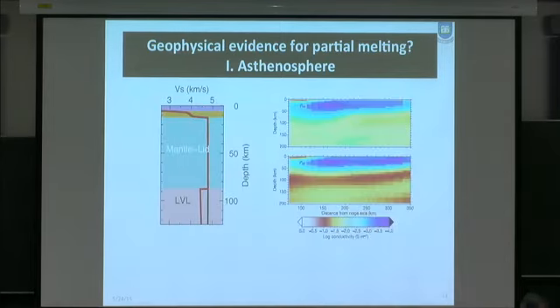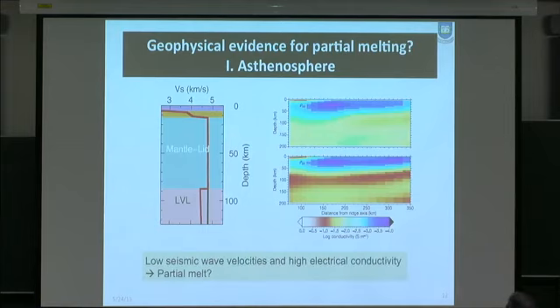Geophysical evidence for partial melting. There are a few observations. One is the seismic velocity drop at the lithosphere-asthenosphere boundary, which is often attributed to the presence of melt. And also, recently, there are some observations from electromagnetic induction studies to find some high conductivity layer corresponding to the asthenosphere. And then the question is, are those low velocity and high conductivity, are they the results of partial melting or some other processes?